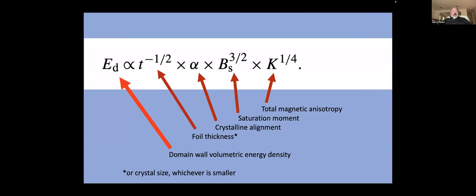Newer sensors are likely to use thicker foils, and as a result, that's one control on making these things quieter. Alpha over here is just a symbol I've used for the crystal alignment. There's been a little bit of study to demonstrate that if you can get the magnetic alignment of these crystals more along the direction you want to measure, it's going to do better.